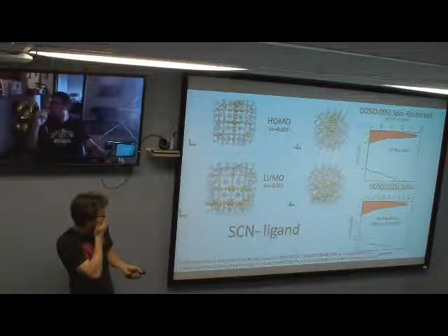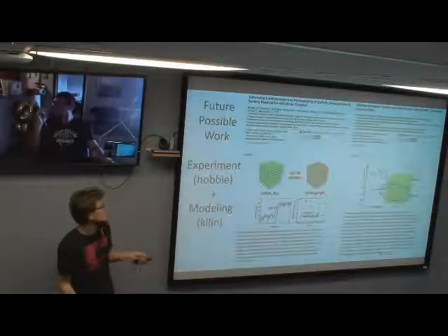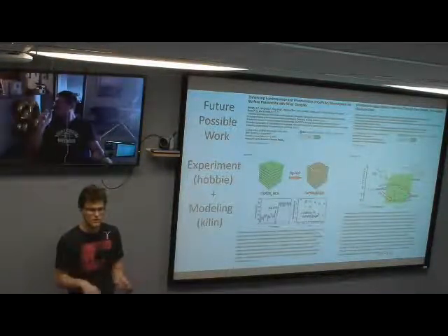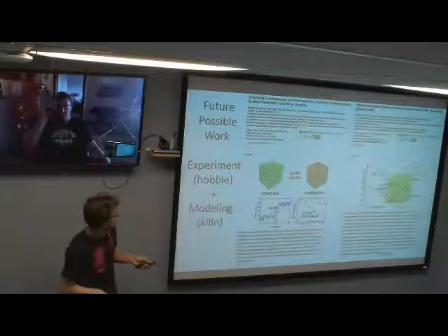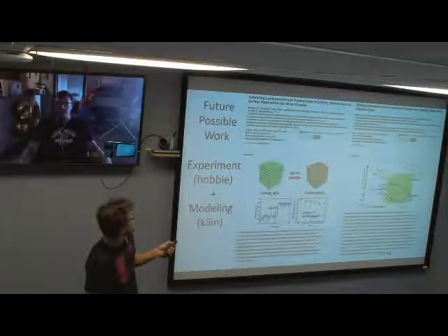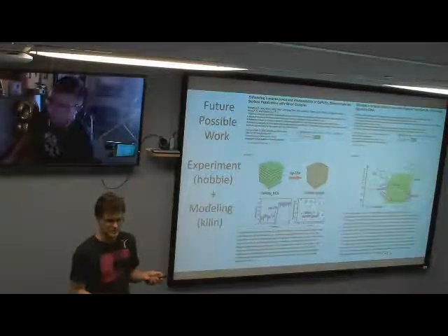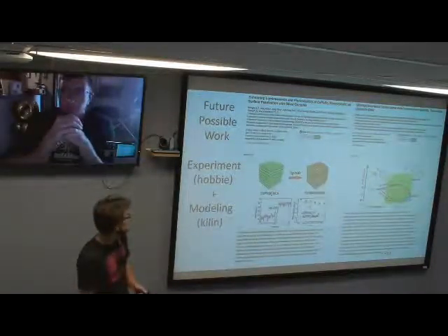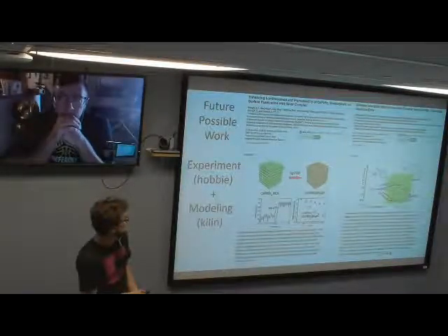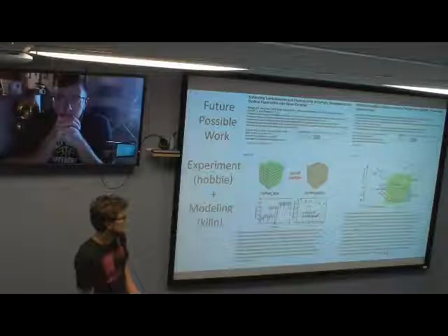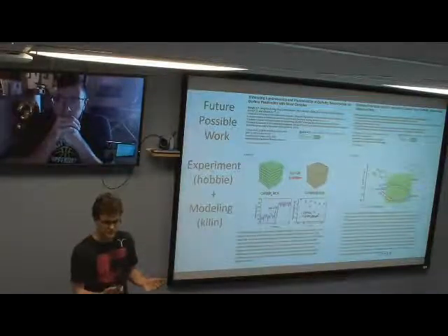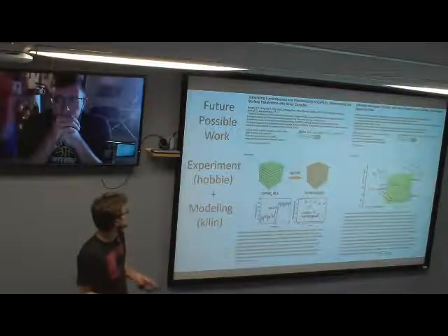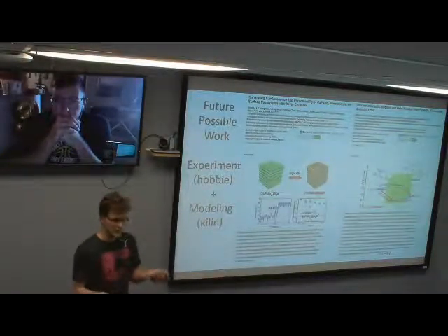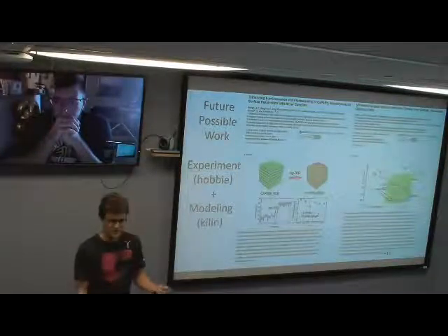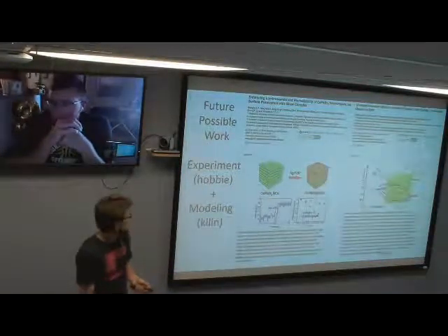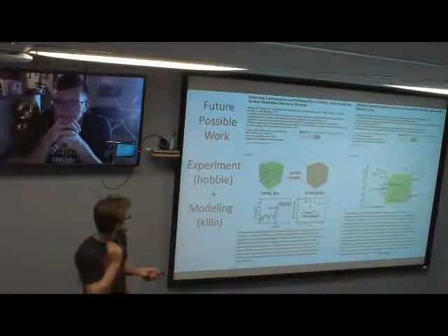So that's some preliminary work from that group, but also future possible work. There are all sorts of other possible ligands for these systems. Silver complexes have been used in cadmium selenide, so it was a natural selection to try those as passivating ligands for perovskite quantum dots. Other groups have attached hole transfer or electron transfer ligands to the surface, so those could be possible. We can work with the experimental group to have experimental and computational insight into passivating and improving photoluminescence properties of these quantum dots.